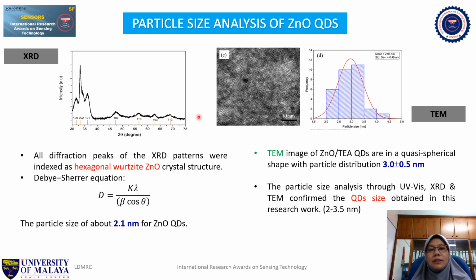Particle size analysis of zinc oxide is also performed by using XRD and TEM. From XRD, it indicates that the structure of the zinc oxide quantum dots that we synthesize is hexagonal wurtzite. By using the Debye-Scherrer equation, we calculate the particle size, which is about 2.1 nanometer, not far off from what we have obtained by using the mathematical model. From TEM images and the distribution of the particle size, we determine that the quasi-spherical zinc oxide is around 3 plus minus 0.5 nanometer. So from the results that we obtain through UV-Vis, XRD, and TEM, we can confirm that the quantum dot size that we produce is around 2 to 3.5 nanometer.